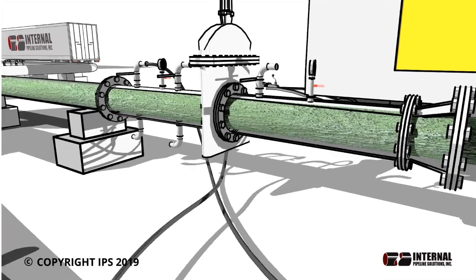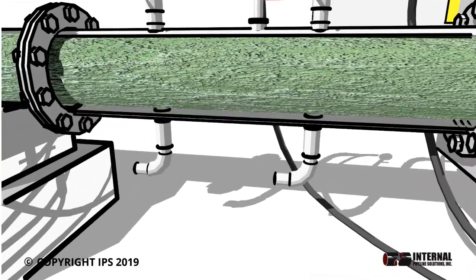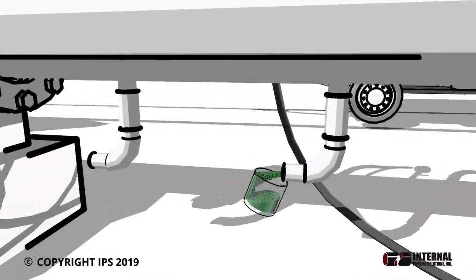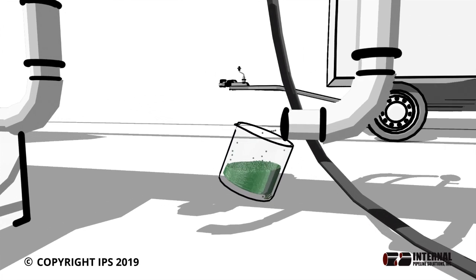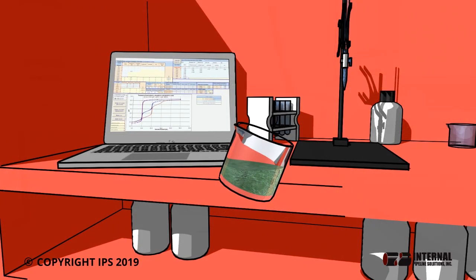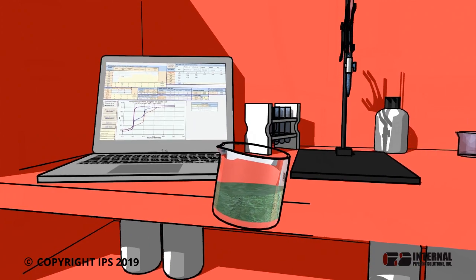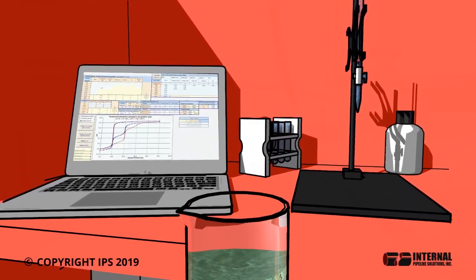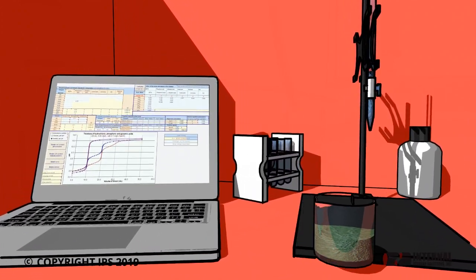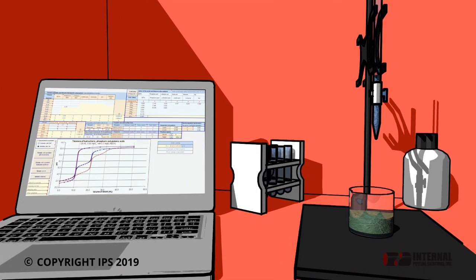IPS collects samples from each cleaning run for analysis. The acid is titrated to monitor changes in concentration. As the acid reacts with oxidation and scale, the concentration will deplete. In other words, the point at which the acid concentration is no longer depleting represents that there is nothing left on the pipeline surface to react with.